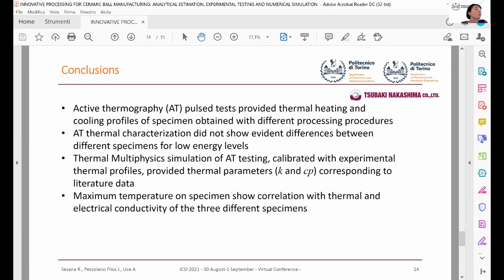Then the thermal multiphysics simulation of active thermography testing, calibrated with the experimental thermal profile, provided the thermal parameters, k and Cp, corresponding to literature data. Last, the maximum temperature on specimen shows correlation with thermal and electrical conductivity of the three different specimens.